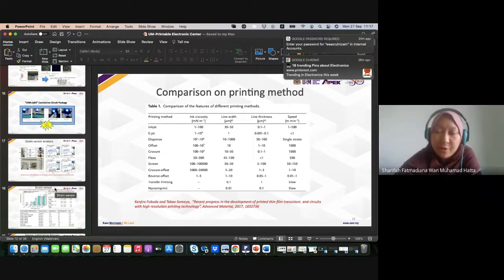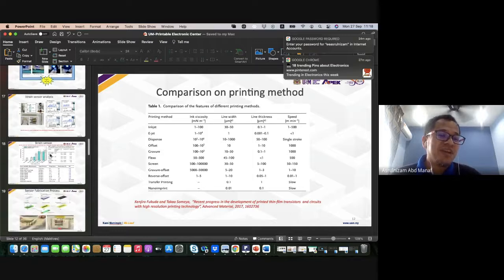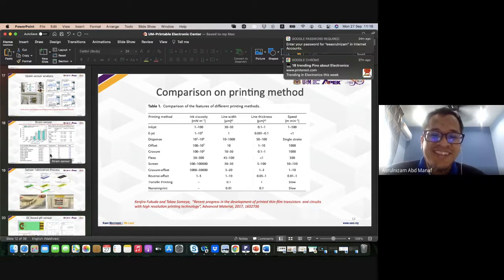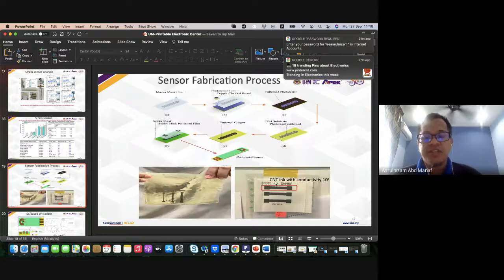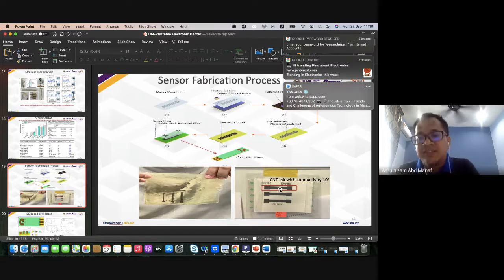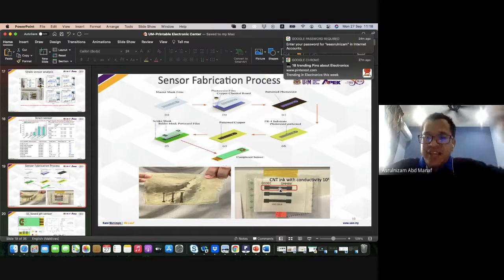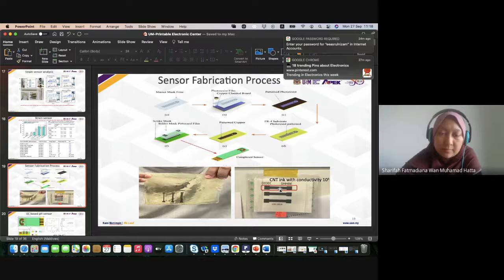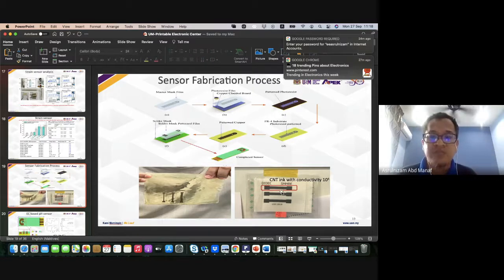Okay. And then for your smart bandage, you directly printed on the cotton bandage, is that right? Yeah. Any specific issues you face when printing on textile? Of course. The first is connectivity. Because when you have cotton, when we do the printing, a single layer should give connectivity, but no, we need multiple layers. One layer still has gaps. That's why in some cases we do about 20 layers.